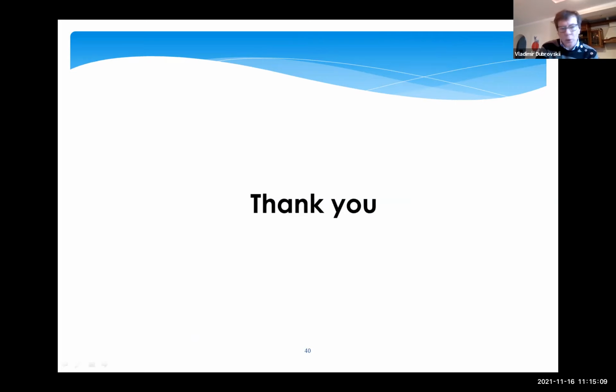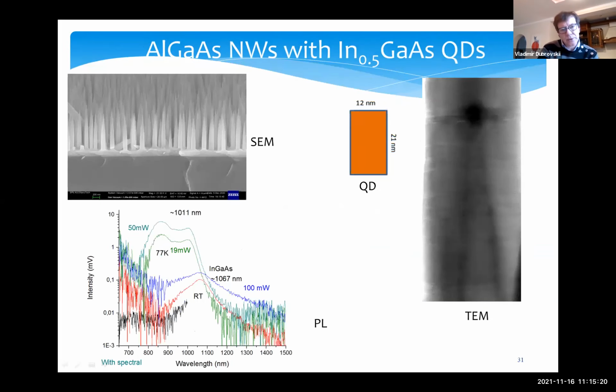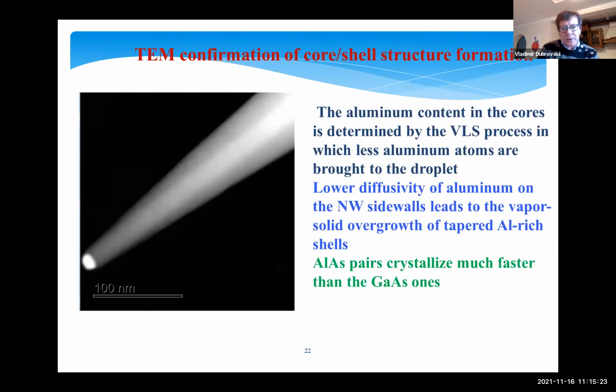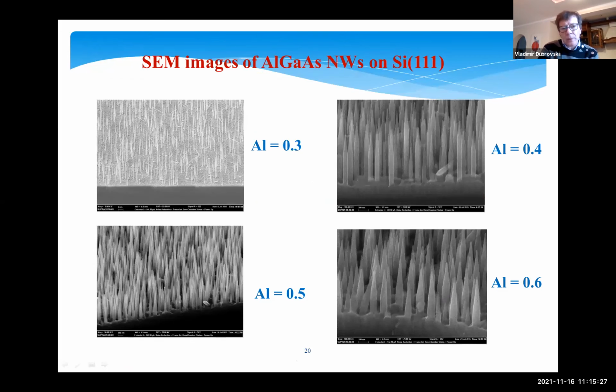Thank you very much, Rodion, for this excellent talk. I have a question. Most of your AlGaAs nanowires are strongly tapered in the top sections. What is the reason for that? Is it due to a shell forming after the cylindrical core has been grown? Yeah, you are right, absolutely right. We think the same about this phenomenon, because the bottom of the nanowires is present on the substrate for much more time than the top of the nanowire. So it's because of the shell growing after. Okay, thanks.